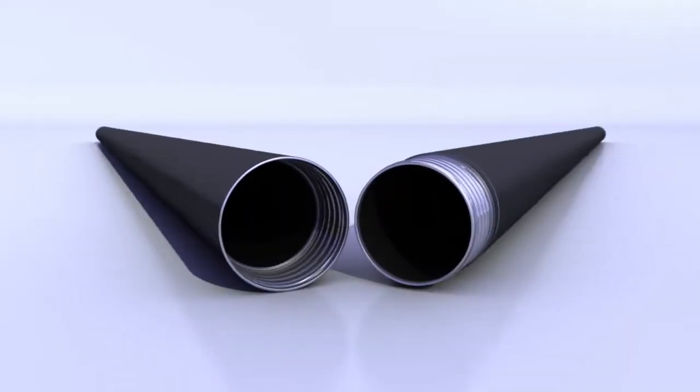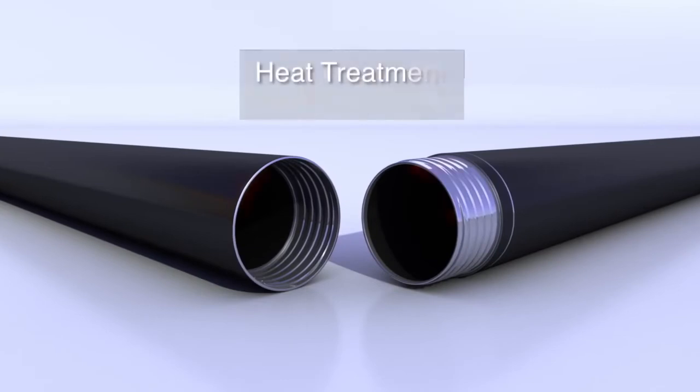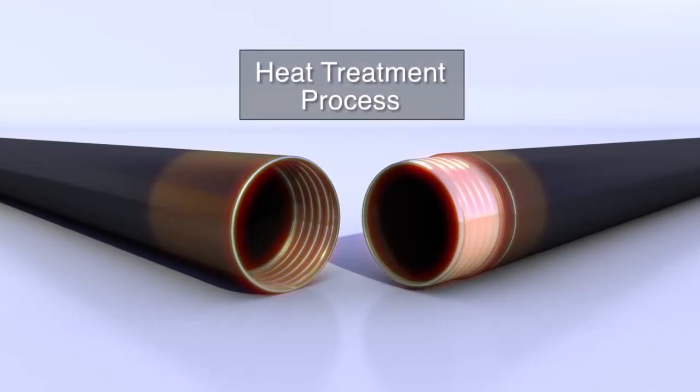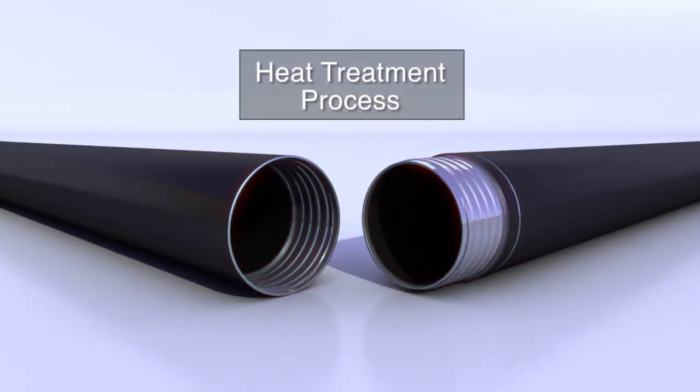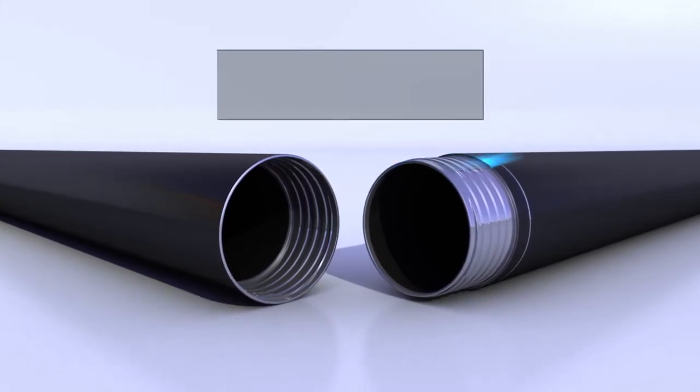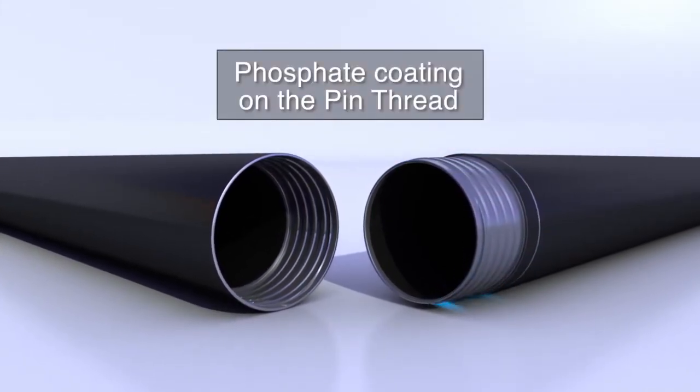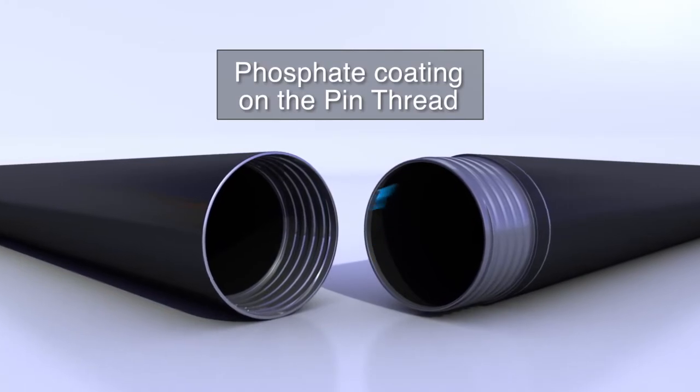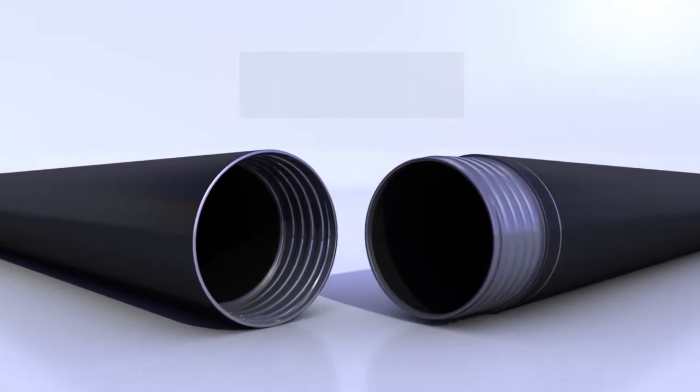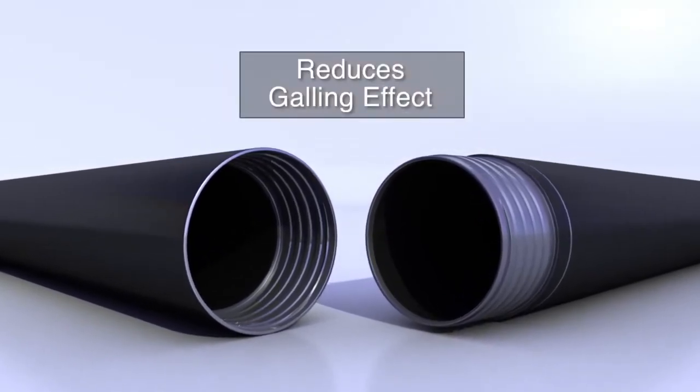In terms of manufacturing, heat treatment is performed located at each end of the bar. Then a phosphate surface treatment is applied to the pin end to create an anti-friction surface which diminishes wear and reduces the effect on successive galling.